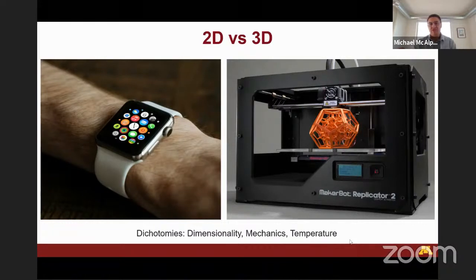But there's also the fact that the silicon needs to be crystallized to be a single crystal. That's a temperature requirement of over 1,000 degrees C, which is completely incompatible with biology, which can only withstand, DNA can go up to maybe 40 or 50 C before it denatures. But then there's also the dimensionality mismatch. All of photolithography and semiconductor processing is planar, right? And biology, from the scale of DNA, proteins, all the way up to organisms, is all three-dimensional, right? So there's that dimensionality mismatch. It's okay for a smartwatch when you have this two-dimensional interface, but if you could take it to the third dimension, you might be able to grow electronics and biology together on the same common platform.